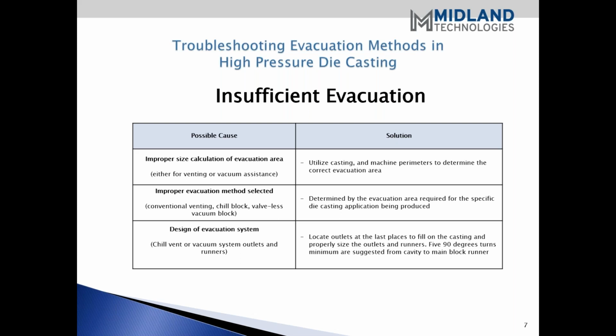And Larry, maybe you can talk a little bit about if you have an evacuation area that you determine, but what if you have too large of an evacuation area? What issues can be involved? Right, that's pretty common. Back in the day, and I think it probably occurs today to some degree too, we used to call it cracking the die or venting the die or letting the die breathe. What tends to happen, of course, is if you have an excessive amount of area to evacuate, you end up evacuating the cavity fine, but the problem is that the metal never sees the proper pressures required to pack the metal out at the end of shot. Subsequently, you've got a casting that appears real nice on the exterior, but is full of pores on the interior because you haven't done that.